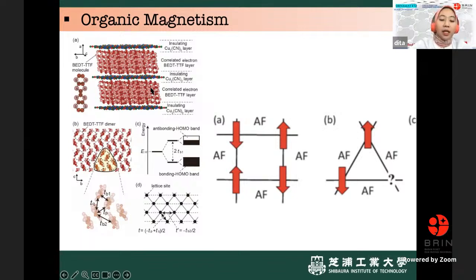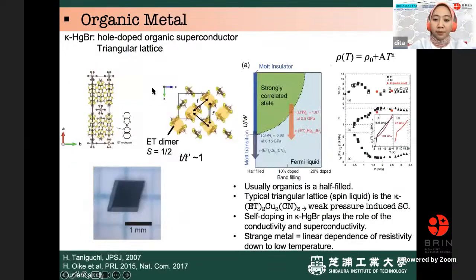So this conducting unit, which we call a dimer here, is in the conducting layer, because it has a layer of insulating and conducting layer. So we have this kind of structure in the organic metal. I choose one organic metal, which is a little bit strange because of the situation in this material: it has a triangular lattice like this, a perfectly triangular lattice in the dimer. So this is the crystal.